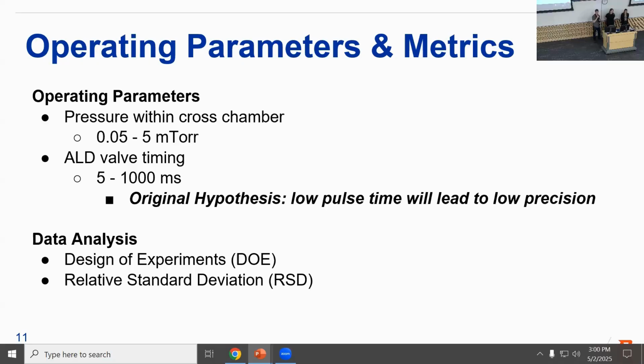So our original hypothesis was that as we got to that extremely low pulse time, reaching the limits of that valve, we would get low precision because of mechanical inconsistencies within the valve when it's nearing the limits of its specs. To investigate this hypothesis, we did a couple of data analysis methods. We did DOE. This gives us really the magnitude of the effect of each of these parameters on the resultant gas dosage. And we also did an RSD analysis, a relative standard deviation. This is simply the standard deviation divided by the mean to normalize it.